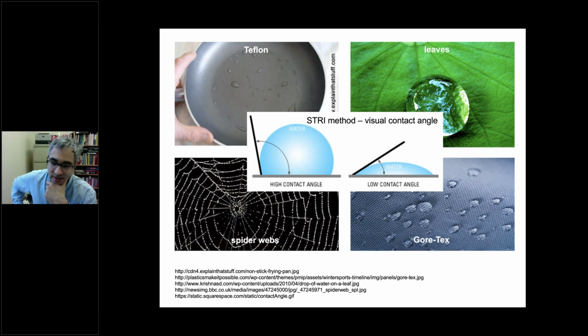Now, the problem with this definition is that it's too macroscopic. In the slides that I'm about to show you, I hope to convince you that this is not a sufficient definition because it doesn't give us enough information. On the one hand, if you look at a material which has failed after some time in the field, you can see that the hydrophobic nature has decreased because the contact angle has dropped. But this really is not a very good predictor, because we don't see a change in the contact angle of materials up until that point. So it'd be nice to have a more detailed microscopic description of how the material ages before we get to the point where we see a loss in hydrophobicity and water is no longer beading up on the surface.